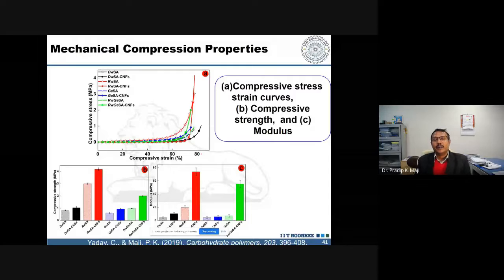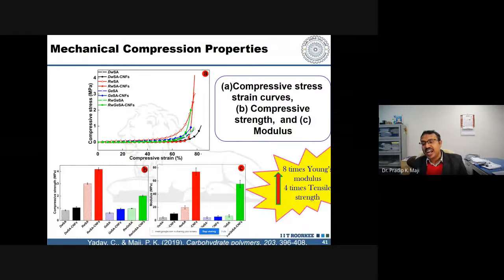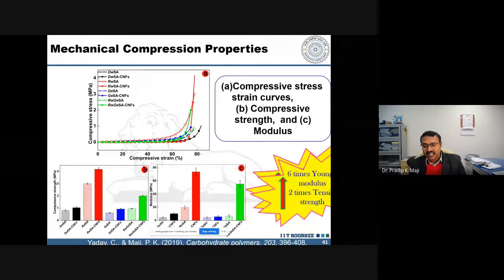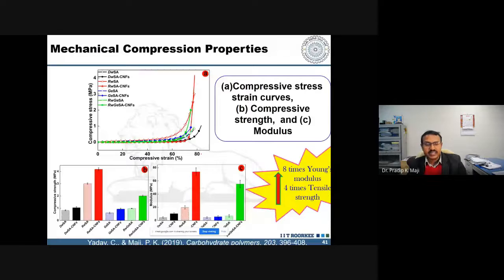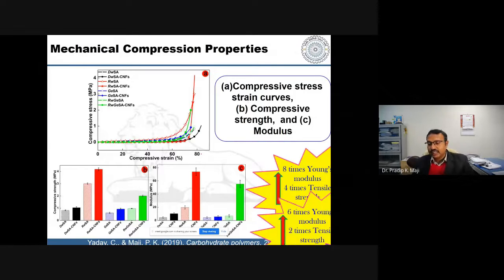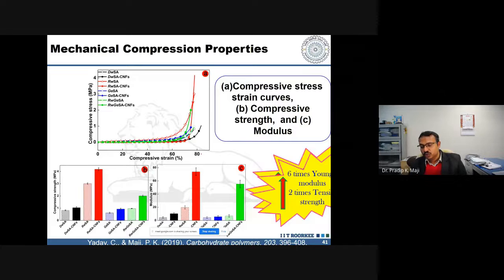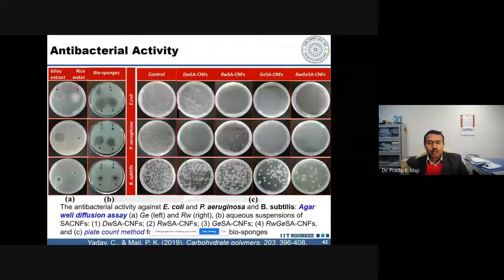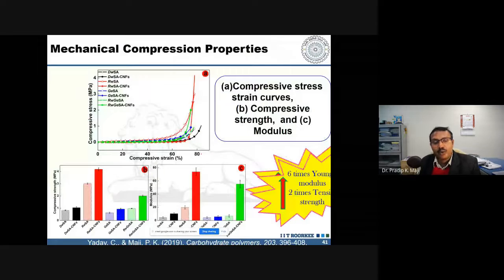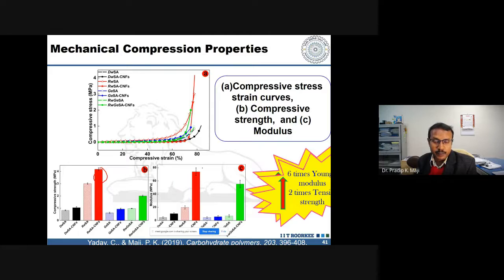So then we checked the compression properties: almost 8 times higher Young's modulus and 4 times higher tensile strength compared to simple alginate. If we add sodium alginate with nanofiber but without the rice water, it comes to 6 times higher modulus, meaning 2 times higher tensile strength. So this combination shows very good mechanical and compressive strength properties.